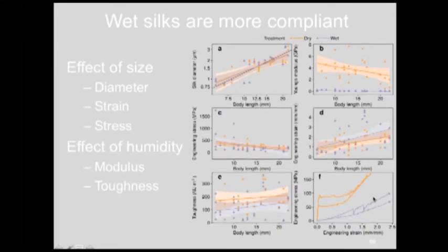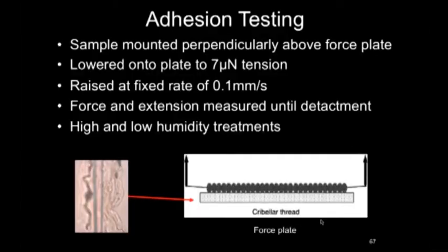Now, our adhesion tests, again, very similar to what we did for glowworm testing. Samples were mounted above the force plate, lowered onto the plate at tension, raised at a fixed rate, where we measured force and extension up until fibers detached, also at these high and low humidities.